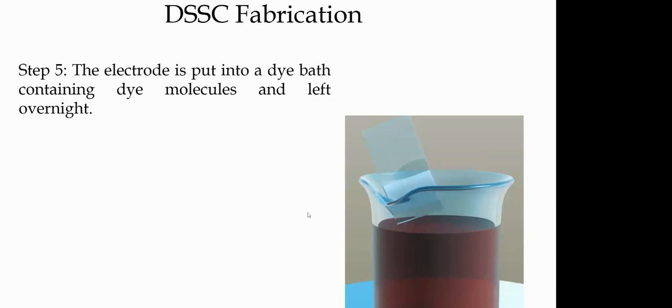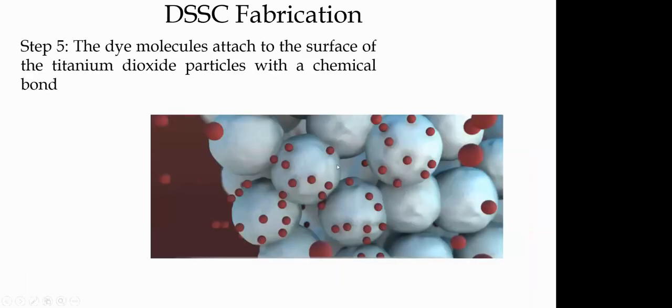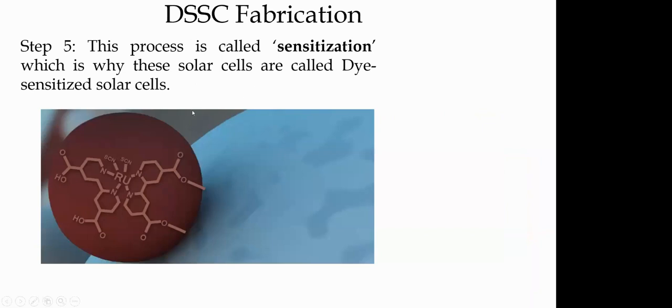In this case, you have a dye solution. You just dip it, because you have these nanoparticles which are porous in nature. So the dye should go and stick physically to all these nanoparticles and cover the maximum area, so that a large number of dye molecules are available. This is the schematic picture of how they are assembled on TiO2 nanoparticles. Then this process that we have done so far is called sensitization.